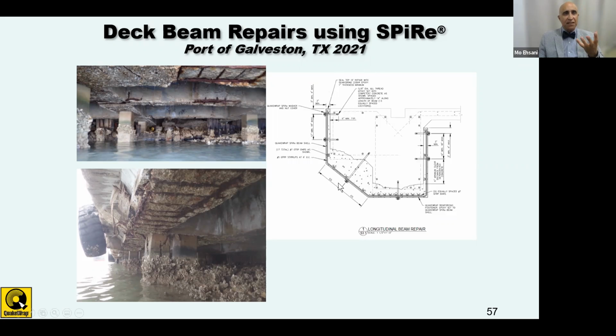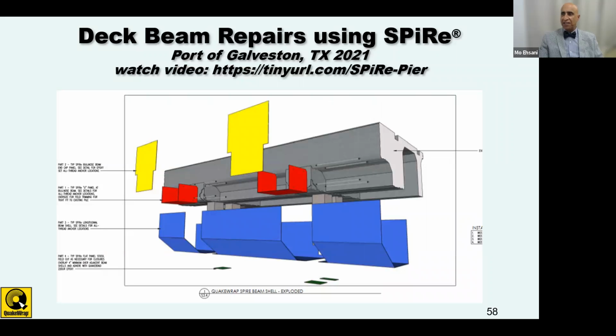And at the end, when this repair is completed, keep in mind that now we have a shell of impervious material around the structure, which not only helps us during the construction, but will stay there as a permanent protection for the underside of this pier. So no more oxygen or corrosion will have access to this, and the corrosion rate would significantly be reduced. And as you see here, this is a rendering of what these panels would look like. We can make them in different shapes based on the point of application, and they're all lifted and put in place like that. So with that, we've come to the end of my presentation.